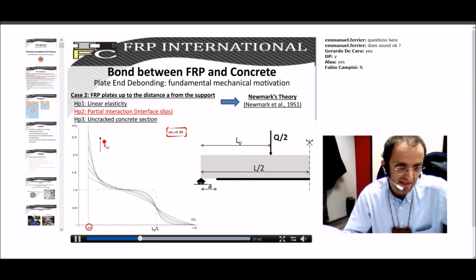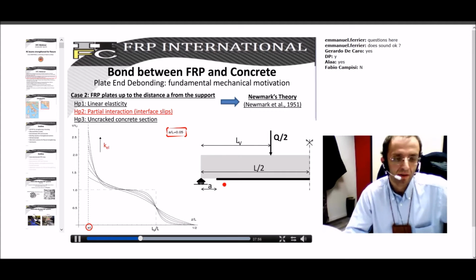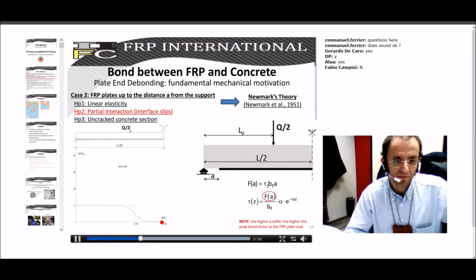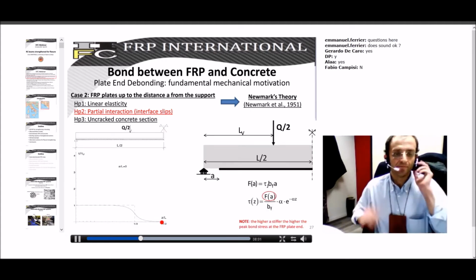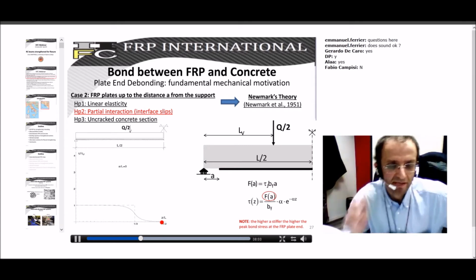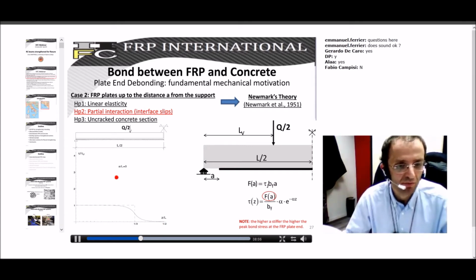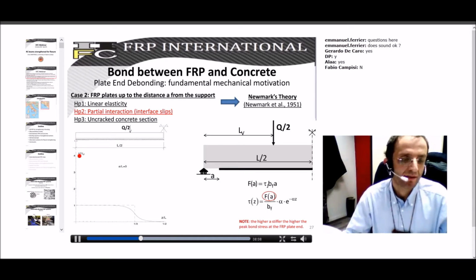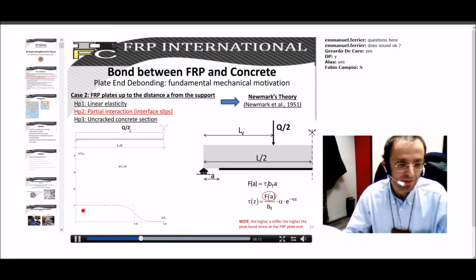If K elastic increases, you have an increase in the peak here. And this is due to AL, so to this distance between the actual cutoff section and the theoretical support. So as you see here, you can maybe have a more physically based intuition of this phenomenon. If you have a complete strengthening, you have this quasi-Jourawski solution with some smooth transition depending on the partial interaction.